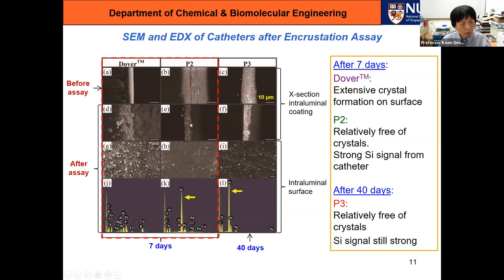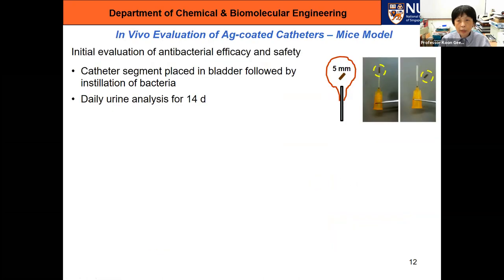Now we compare the P2. After 7 days, we can still see the coating. The surface is not as crowded with crystals as the Dover. And you can still see a very strong silicon signal. We see some calcium, but we can still see a strong silicon signal. That means the substrate is still showing. And this is P3 after 40 days. And you can again see that we have very strong silicon signal compared to the Dover case after only 7 days. So we think that this P3 coating is actually quite good. So we decided to do animal tests.